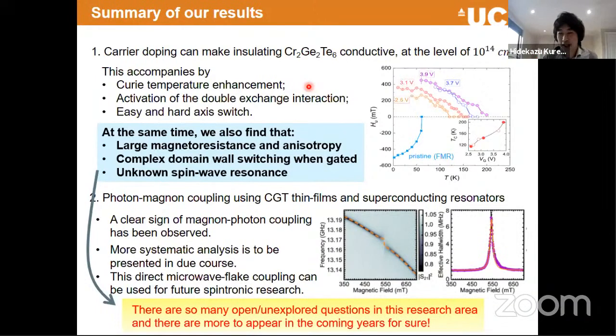Indeed, we can measure it, because that's a bulk sample. I didn't show it, but there are two curves. One is just the undoped CGT, and the other is the one with a tail going down, with the high temperature going down to probably 200 Kelvin. So that represents the doped CGT. So the quick answer is yes, we can measure it, and I hope that we can show these results when we publish the manuscript.